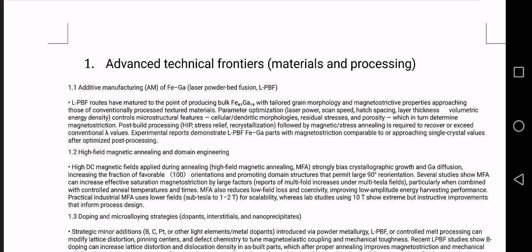However, printing alone is not enough. Why? Because LPBF creates residual stress, porosity, and dendritic microstructures. Therefore, post-processing is essential. This includes hot isostatic pressing (HIP), stress relief annealing, recrystallization, and magnetic or stress annealing. With optimized post-processing, printed FeGa parts can approach single crystal performance.